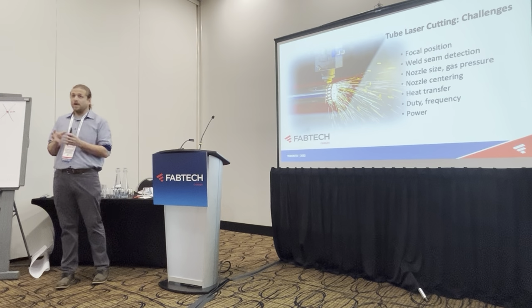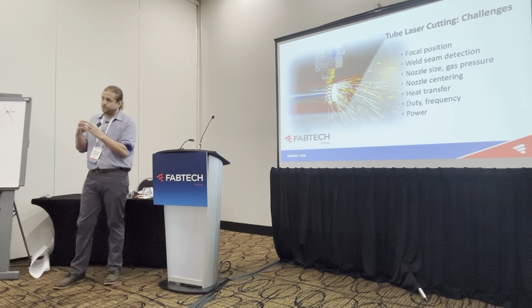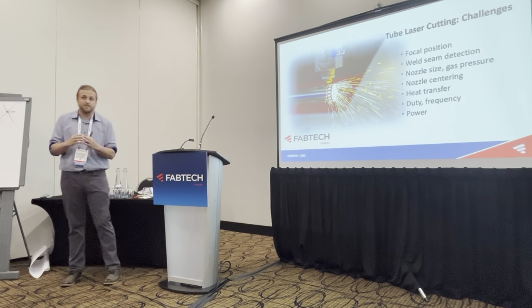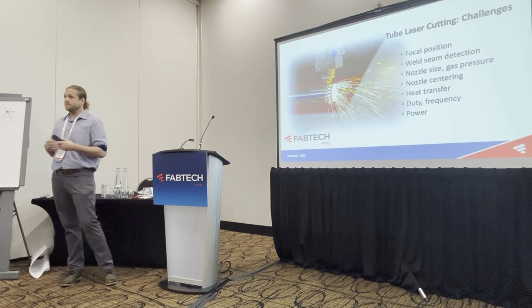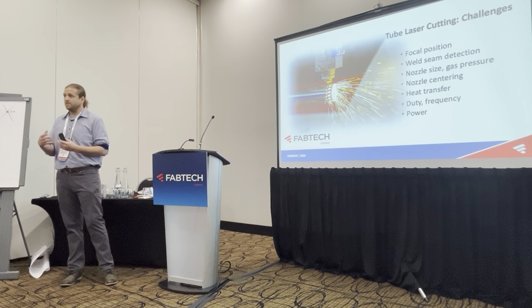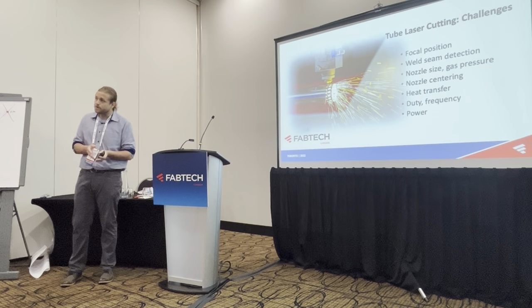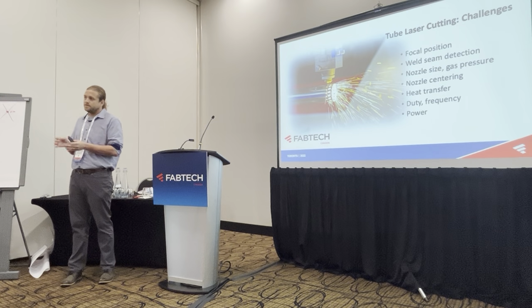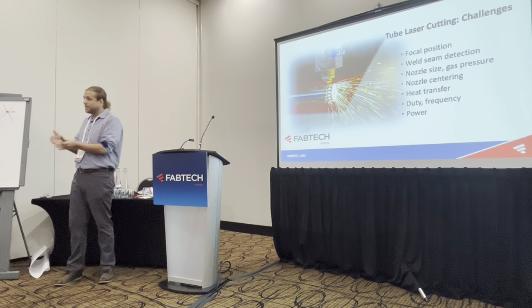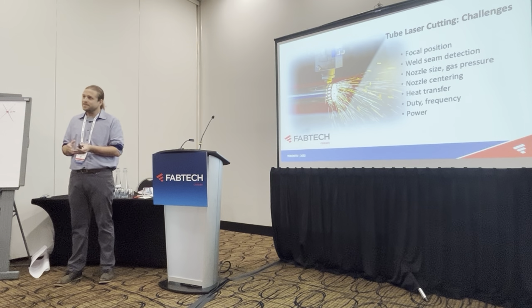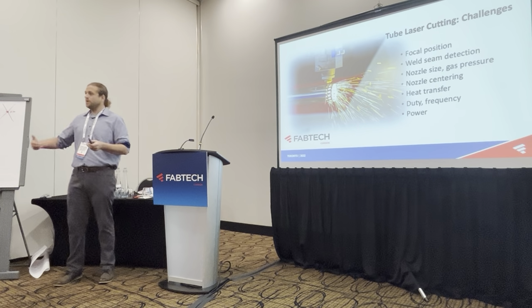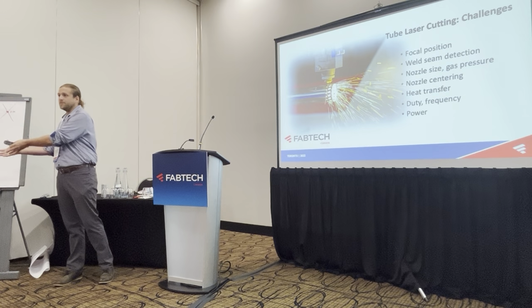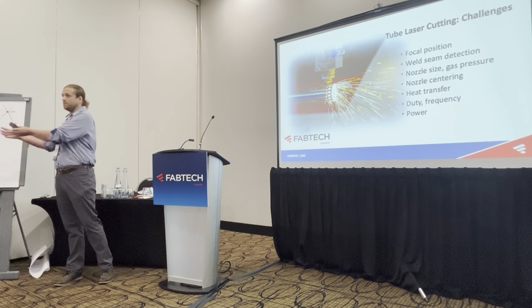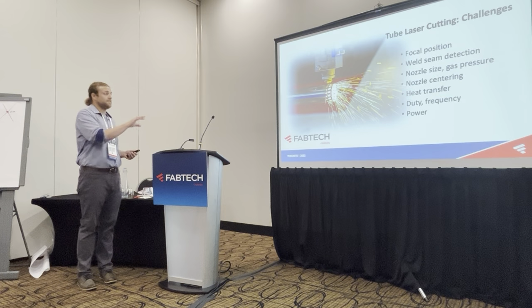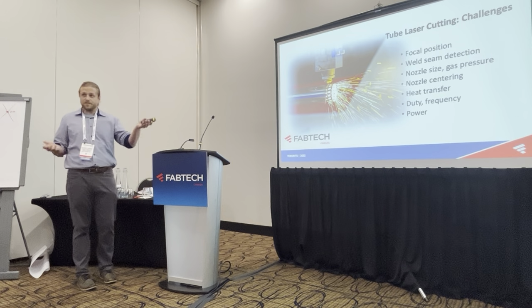So in that case, you have to keep an eye on that cross section of your tube. Again, it's very small cross sections where you can't dissipate the heat fast enough. It travels down the tube, next thing you know, you don't have any parts. It's not even cutting it at that point. You can't adjust for it, because that variable changes, since you actually don't know the temperature of it. So if you made that adjustment, it probably would cut a few again, and then you'd lose the cut because it just keeps continuing to build heat. So that's critical.